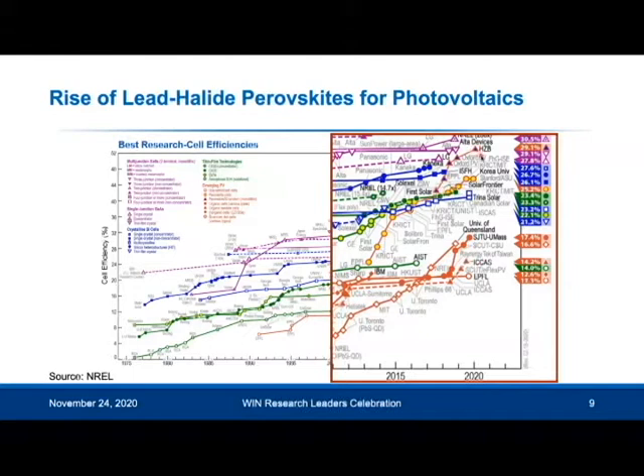The certified highest efficiency is now at 29.1%. And this is larger than the best efficiency for single-junction silicon. It's also larger than the efficiency limit for silicon working by itself. So this is very promising, and people predict that it's realistic and practical to commercialize these perovskite silicon tandems and make large-scale modules that have 35% efficiency in the very near future.